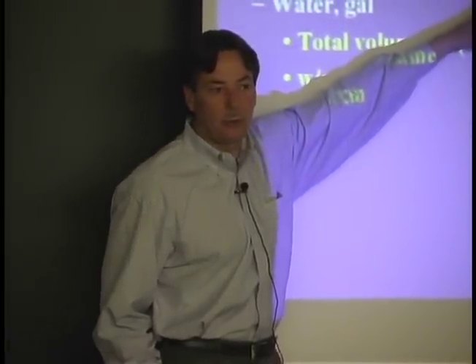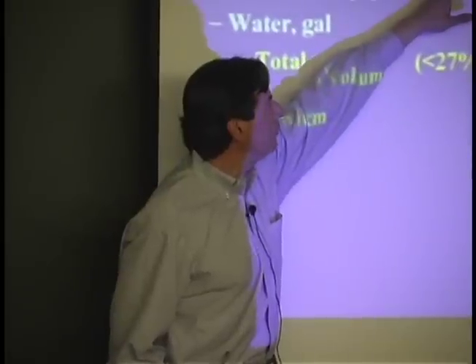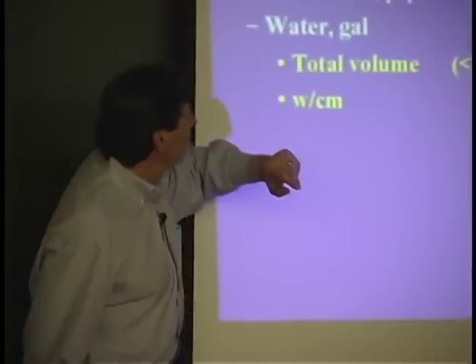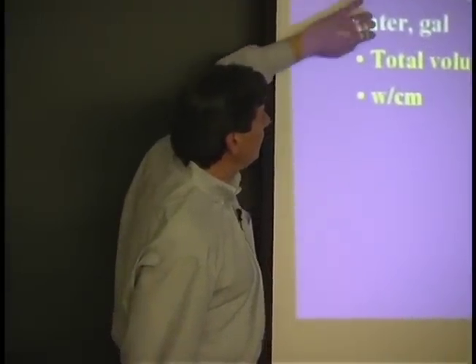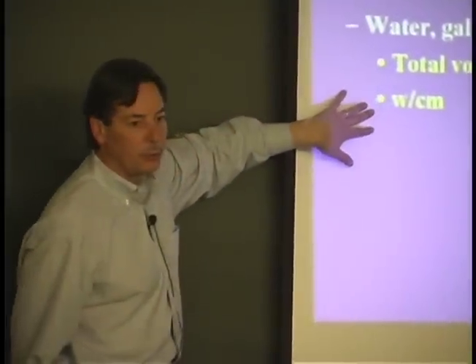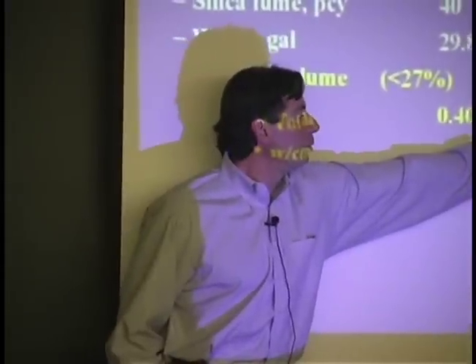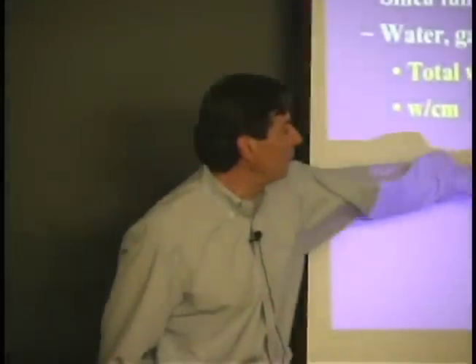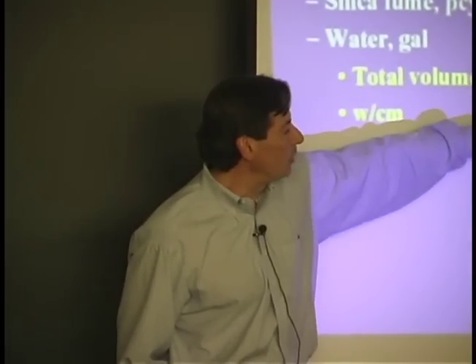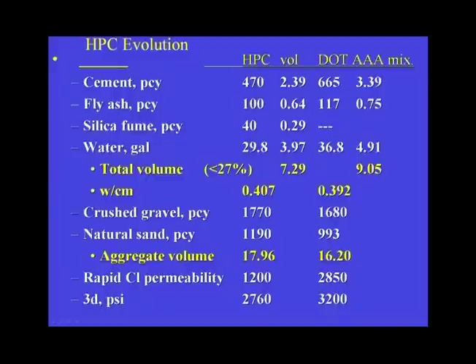They took out 200 pounds of cement and put in 40 pounds here. That's 5-to-1, basically. But when they lowered the cementitious materials, they're only what, 470, 570, 610 pounds of cementitious materials on this water here is only almost a point four water cement ratio. We talked about before low water cement ratios, those type things. Normally lower means better. In this case, their old mix was a lot lower water cement ratio than this mix was. In essence, you would think that this mix would not be as good following that technology, but what it shows was you're able to use more aggregate, larger quantities of the good material in your concrete,